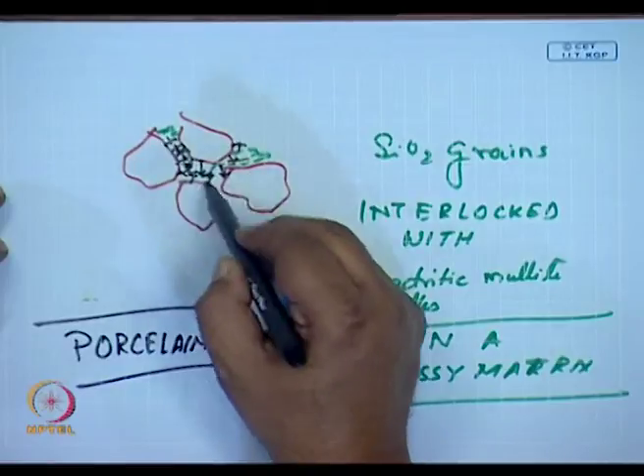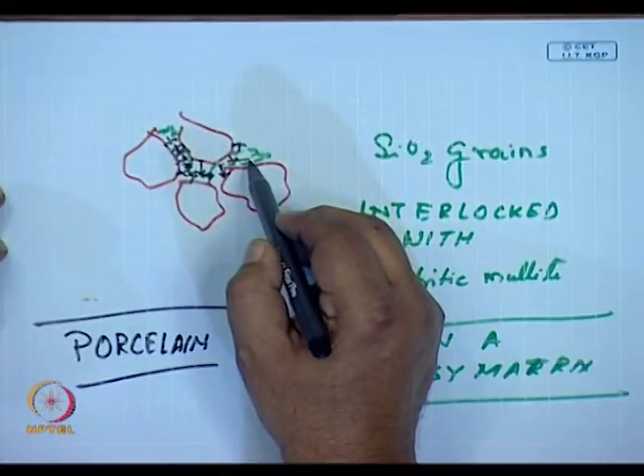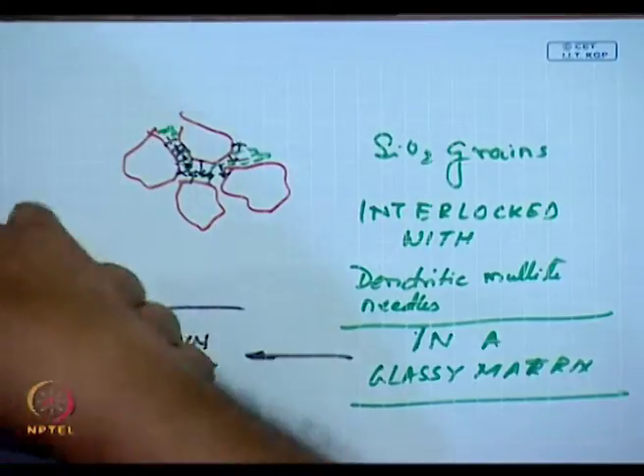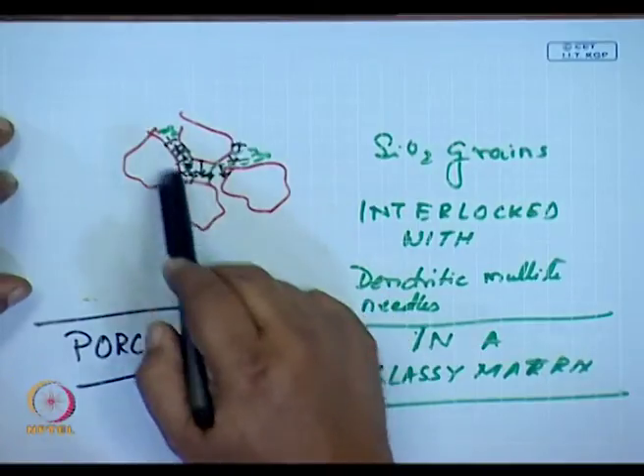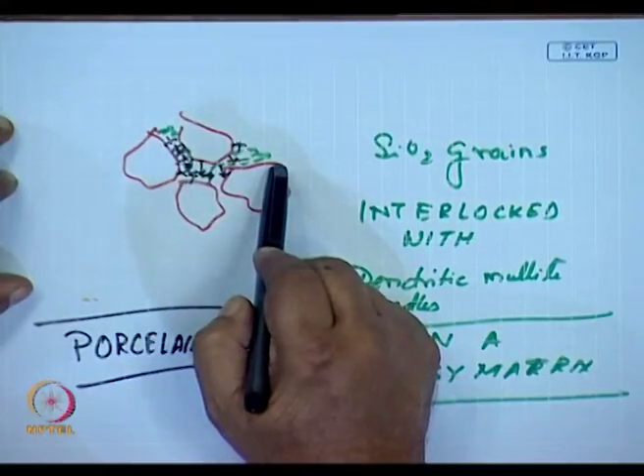It is basically a ceramic body which is held together by the presence of glassy phase in the grain boundaries. So essentially, we may not really expect a decrease in dimension. There can be a decrease. It depends entirely on the volume expansion coefficient of the glassy phase over here.